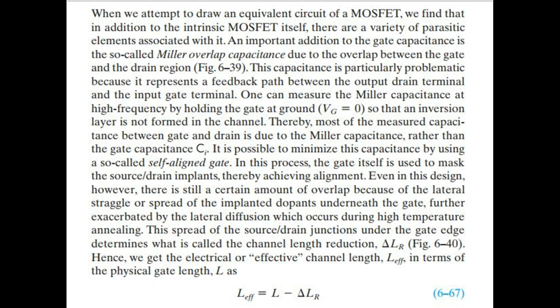In this process, the gate itself is used to mask the source/drain implants, thereby achieving alignment. Even in this design, however, there is still a certain amount of overlap because of the lateral straggle or spread of the implanted dopants underneath the gate, further exacerbated by the lateral diffusion which occurs during high-temperature annealing. This spread of the source/drain junctions under the gate edge determines what is called the channel length reduction, delta LR, Fig 6-40. Hence, we get the electrical or effective channel length, L eff, in terms of the physical gate length, L as